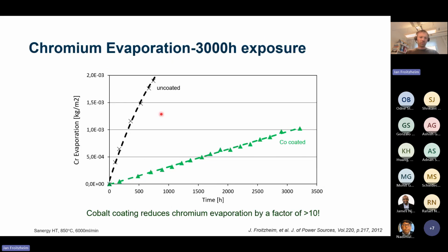This is a plot of chrome evaporation as a function of time, for up to 3,000 hours or a little more. You see the uncoated material up here, and for more than 3,000 hours at 850 degrees C, a pretty challenging temperature, the evaporation rate is reduced by more than a factor of 10, closer to a factor of 50, because at that point we had uncoated edges contributing. So this worked very nicely.